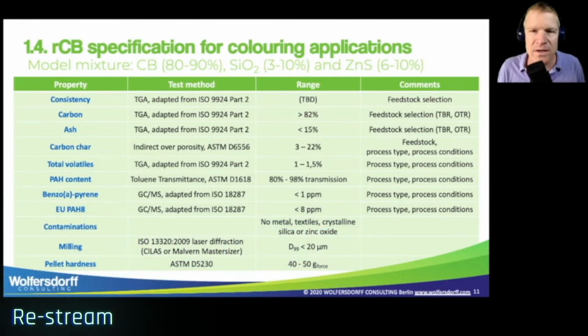Now also we need to pelletize the recovered carbon black. The pelletizing is for convenience of handling, low dust handling, and also for better conveying in pneumatic systems. Here it is important to have a pellet hardness which is not too soft, because then the pellet will break up in transport and the customer will just receive some powder. It shouldn't be too hard either, because then it cannot be broken up in the dispersion processes in polymers.